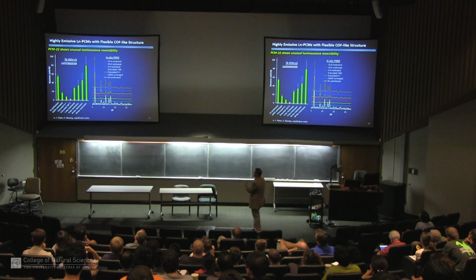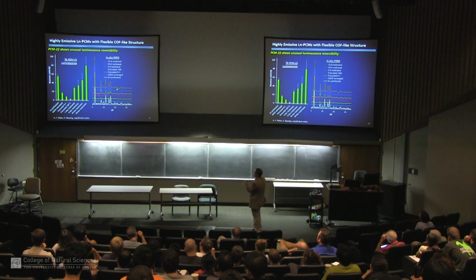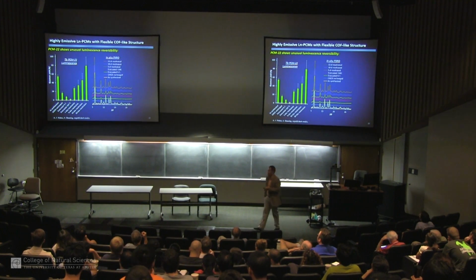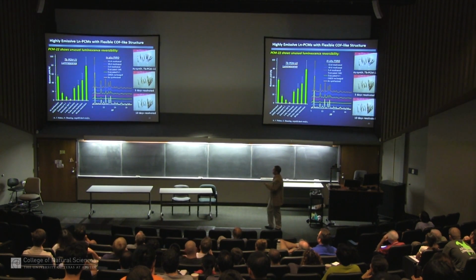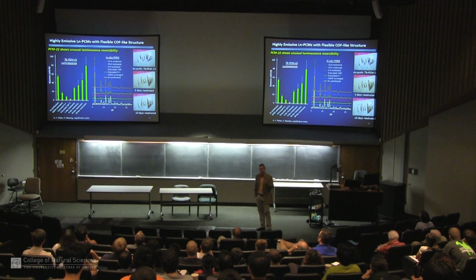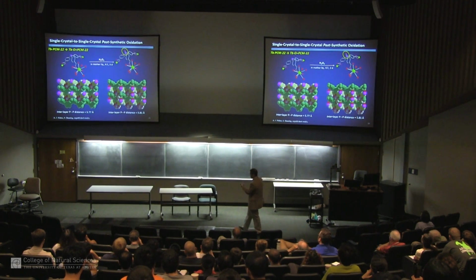And we can see this in the bulk. You can see your crystalline material looks like it's completely amorphous now. And as soon as you're exposed to different solvents, all the crystallinity comes back. So this is a solid state reversible transition. We photographed the crystals of this material in the process over several days to make sure, to answer the question, this is not something dissolving and recrystallizing, because that would definitely be cheating. The crystals don't go anywhere, it is all inside the crystals.